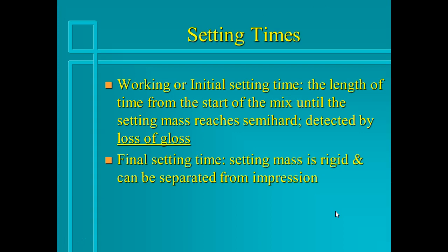Now let's discuss the setting times. When we talk about the working or the initial setting time, we're talking about the length of time from the start of the mix, when you start mixing the product with the water, until the setting mass reaches semi-hard. And this is actually detected by loss of gloss. You will see a loss of gloss.